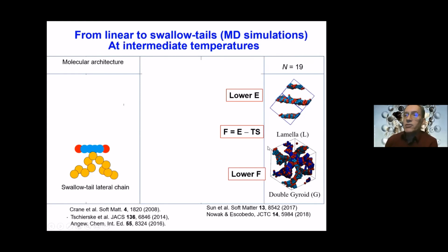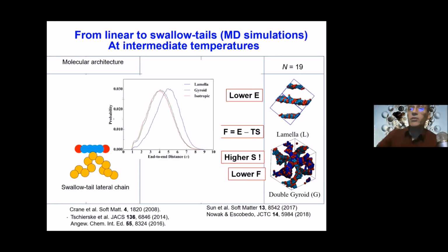But combining these two results and the definition of the free energy, these results are only consistent if the G phase has the higher entropy, because that's what lowers the free energy of this phase. So where is this entropy coming from? It has to be coming from the chains, the lateral chains. And indeed, if you look at the end-to-end distance to see what's the average extension, you will find that these chains, if you put them in this lamellar phase, they will tend to be too stretched. And I told you that chains hate to be stretched because that decreases their conformational entropy. They want to be more relaxed. And it's in the G phase that they are more relaxed, kind of like in the isotropic phase.